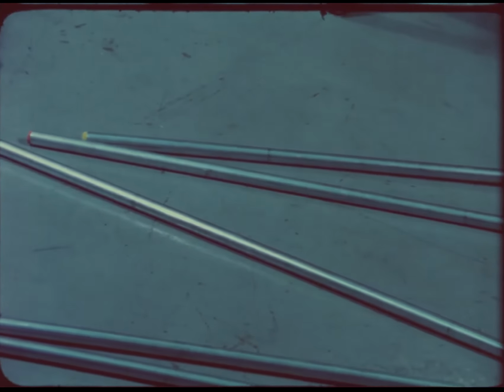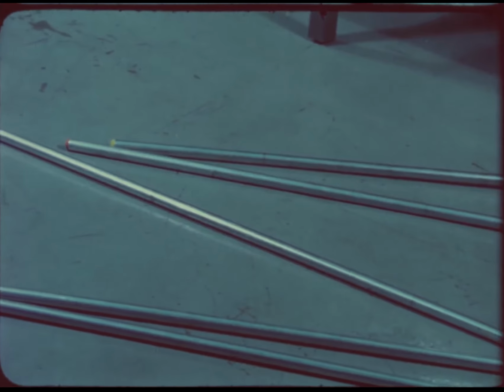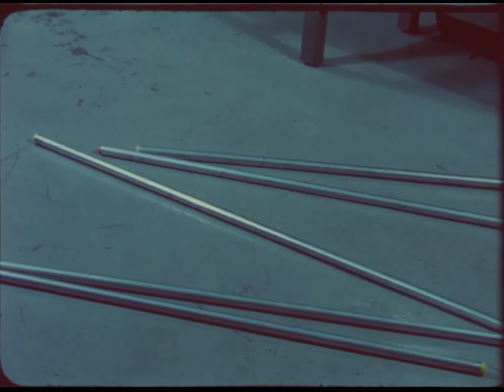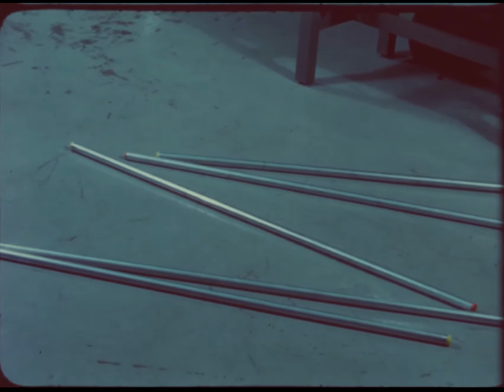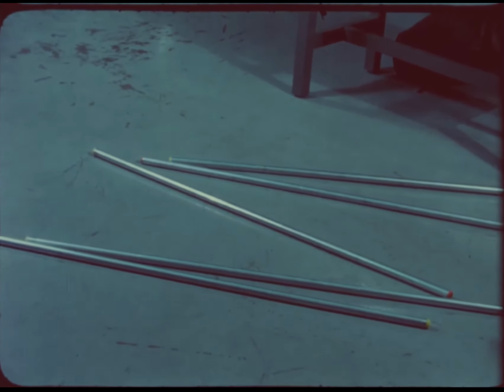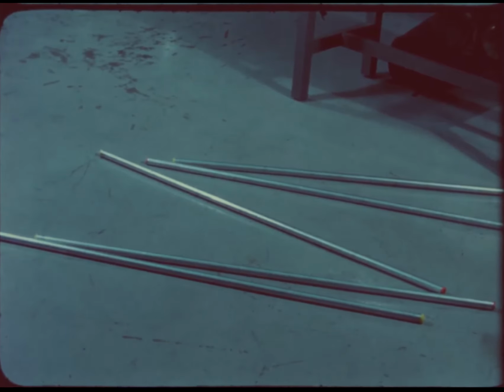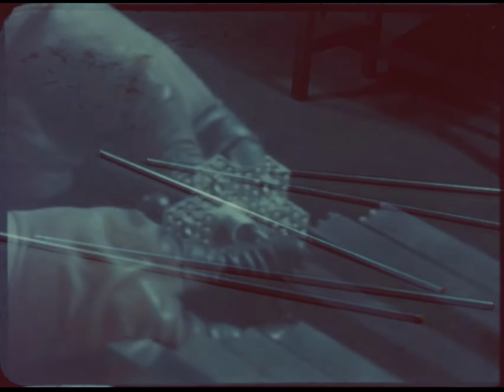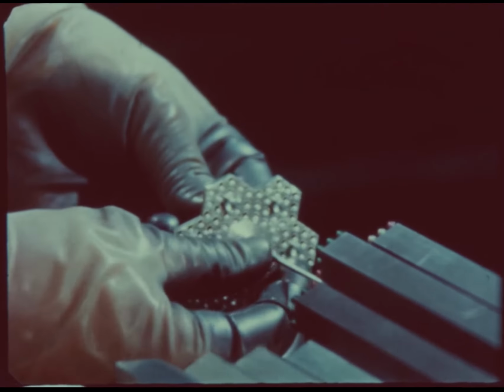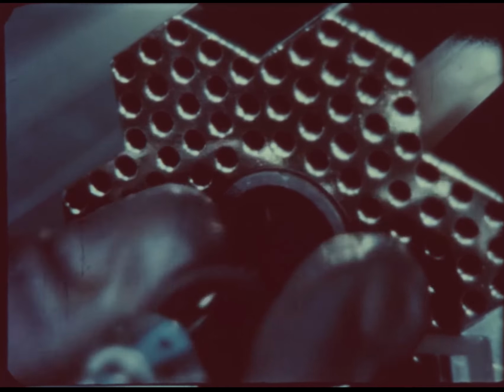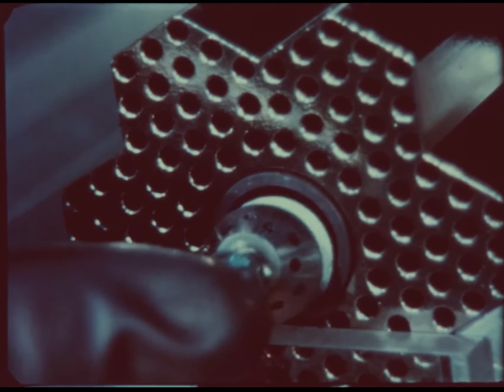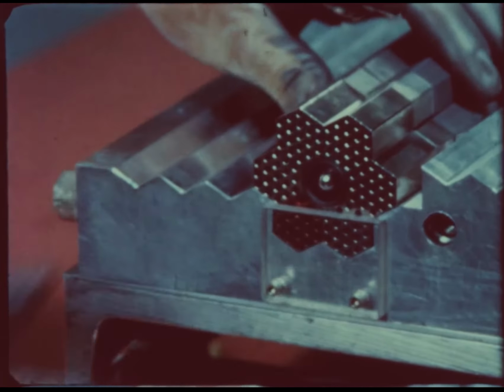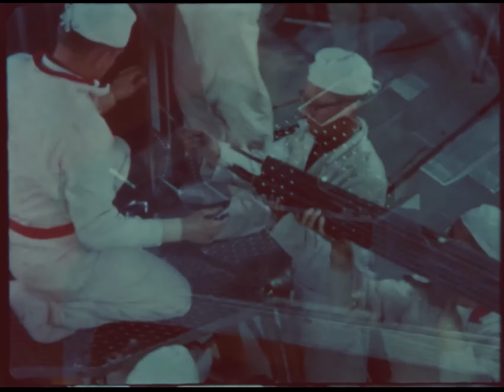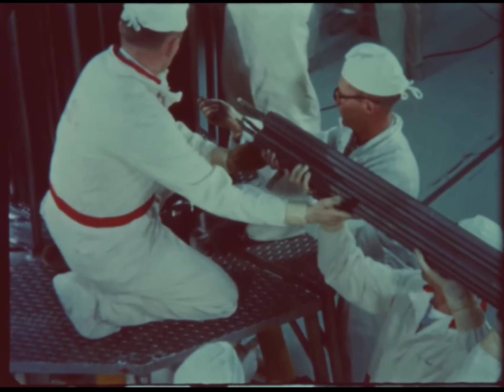Although there is generally a great deal more precaution taken in the handling of fuel elements, an extremely large number have been rejected for every reactor in the Rover series because of damages due to careless handling. At the time of reactor core assembly in Nevada, generally 3 to 5% of the fuel elements received are rejected because of damages. Up to 5% of support blocks received are also rejected.